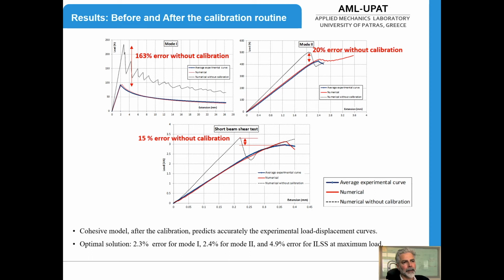If we go to the top right diagram, here you may see the simulation of the mode 2 experiment. The results of the mode 2 experiments are shown with the solid black line. The red line represents the simulation of the mode 2 experiment in case we have used the optimized material parameters. And the dotted line over here is the numerical simulation of the mode 2 experiment in case we have used the reference material parameters. As you may see, there is also a significant difference of close to 20% in the top load in the case of mode 2 experiments. The same situation can be identified also in the case of the interlaminar shear strength experiment.